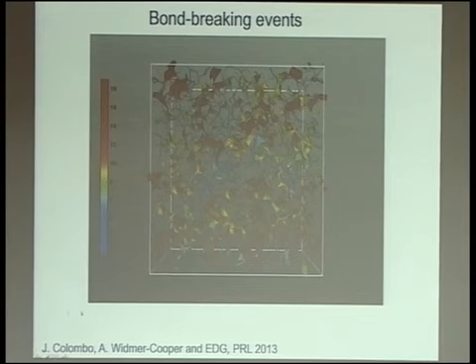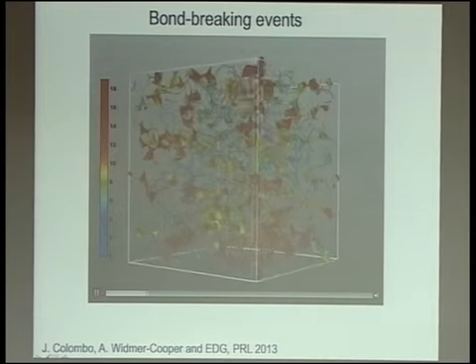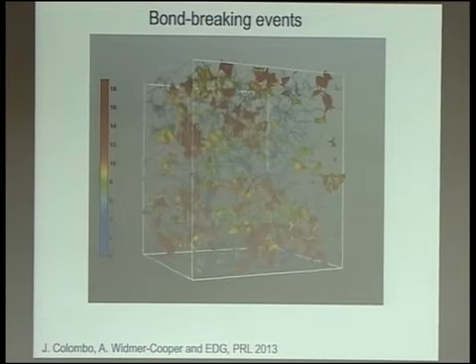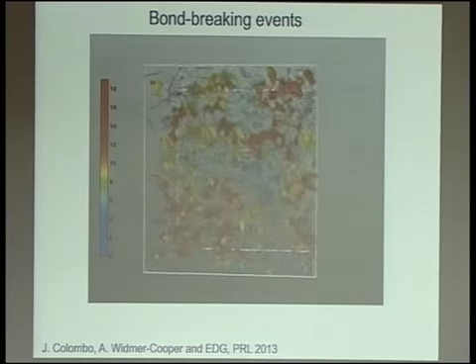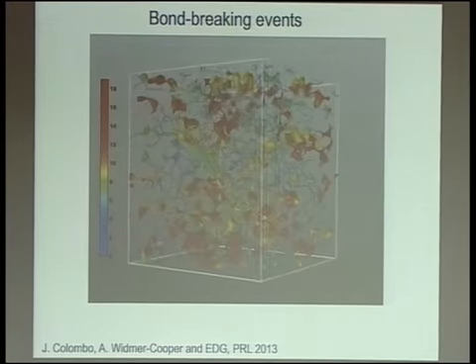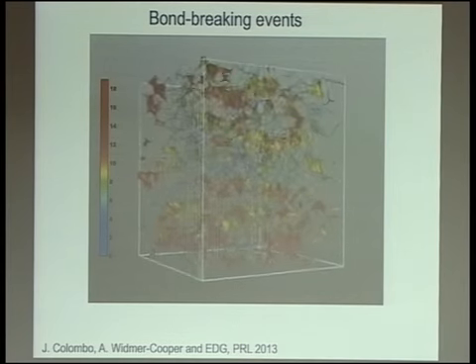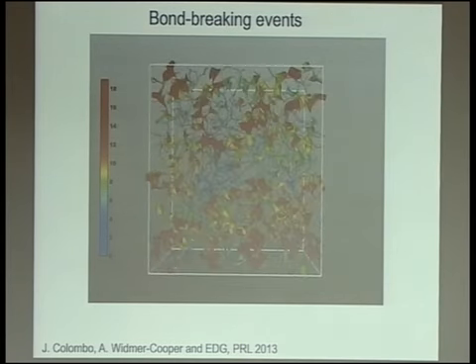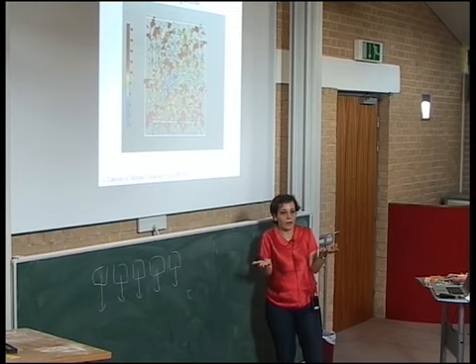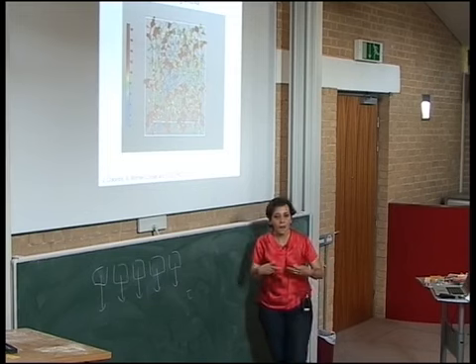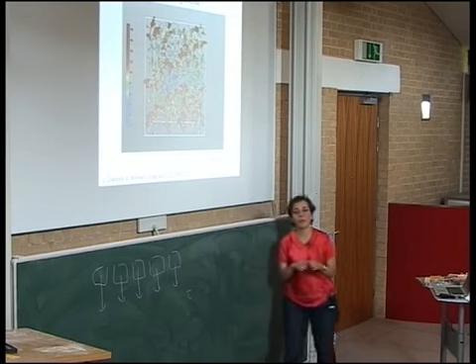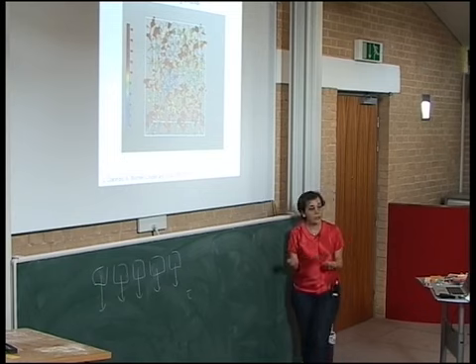And so one thing that you can see, I hope, because maybe the colors are not so nice, is that red things tend to be thicker. So this tells me that the network tends to break in the regions where it's more densely connected. These regions, which are also probably the parts that are most important for getting the mechanical stability, on the other hand seem to be also the regions where things tend to break more likely. And in fact, we can, yes?